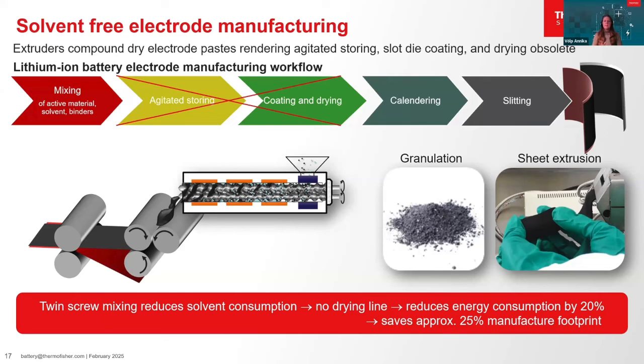Suitable binder formulations like PTFE or PVDF allow the dry cathode granulate mix to be calendared directly onto the current collector foil. PTFE forms fibrils under shear to bind the particles, but the shear must be controlled for proper fibrillation. Sheet extrusion of the electrode material is also possible, providing more uniform dosage of the calender, but it requires about 20% of solvent. Twin screw mixing reduces solvent use, energy, drying costs, and saves space by eliminating the drying line. However, dry electrode processing remains at pilot scale due to challenges in calendering and scale-up. The next slide discusses a study on screw design for dry processing.